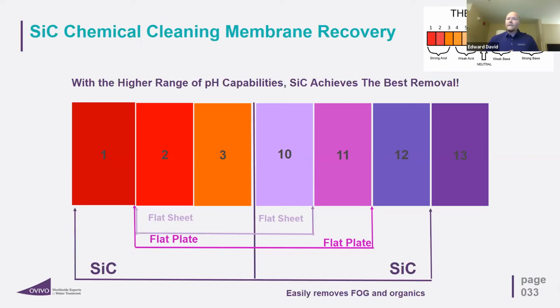The benefit you're going to get with the ceramics, with the SiC product, your window range of operations is going to be 1 to 13. That's a huge difference because now you're hitting it with a strong bleach, and if you need to, you can bump to an oxalic, which till recently we have not been able to do with flat sheet and flat plate.